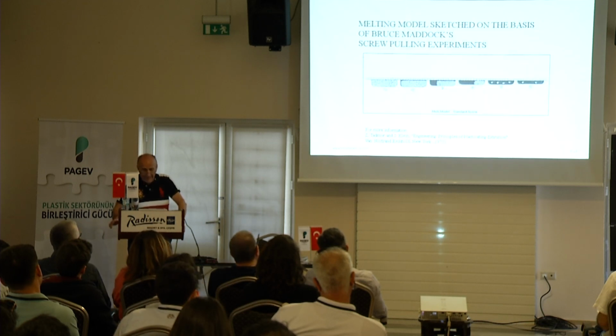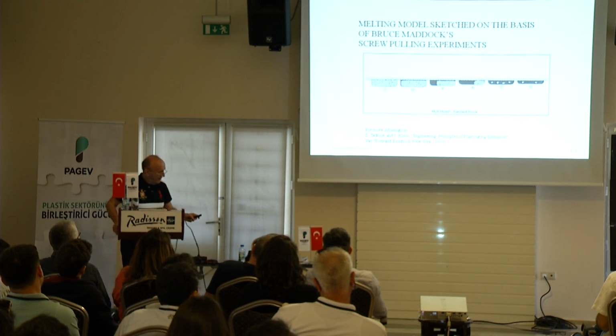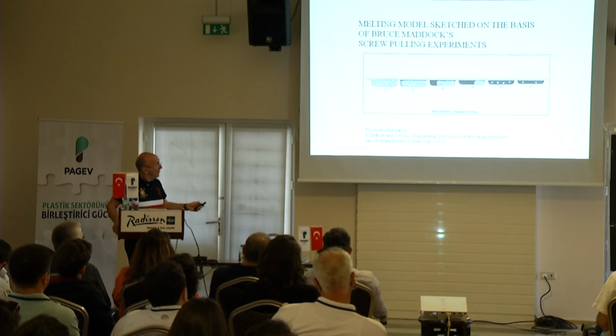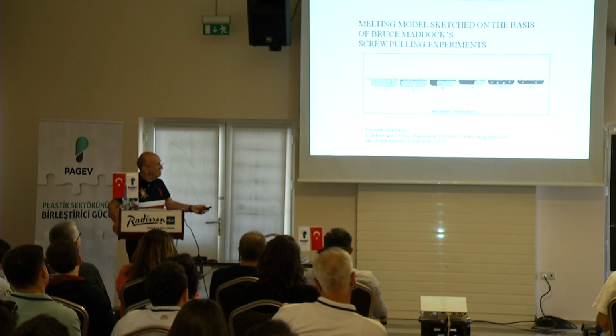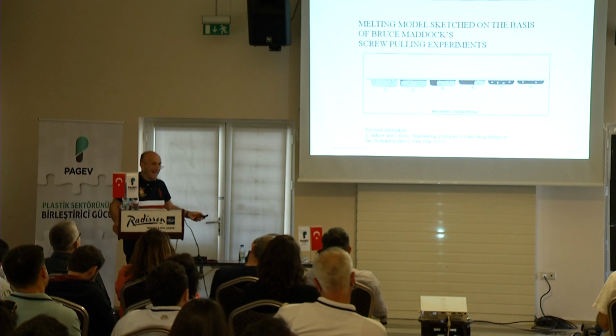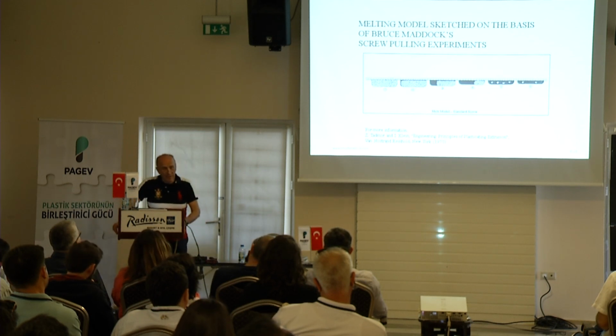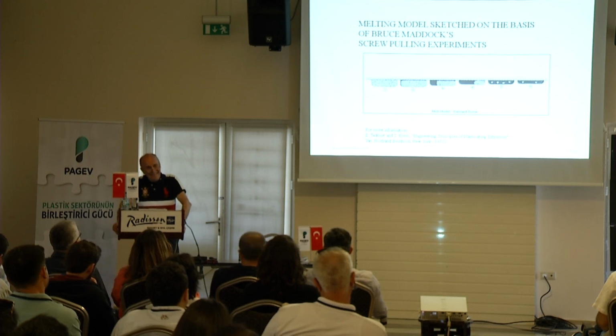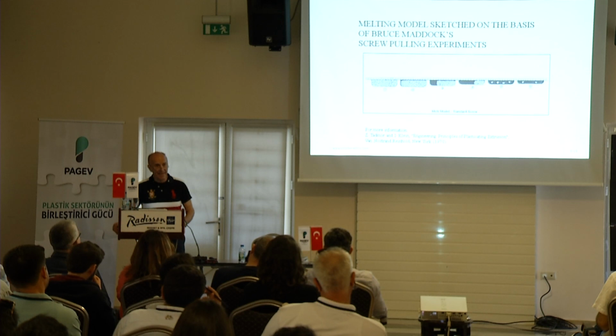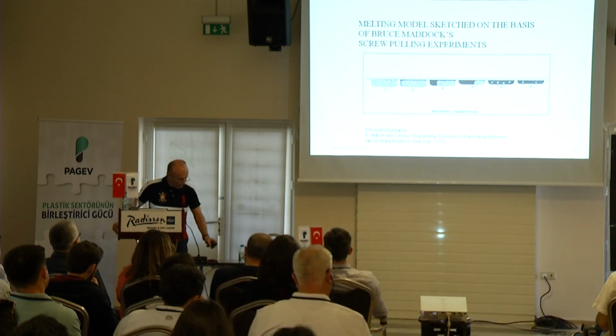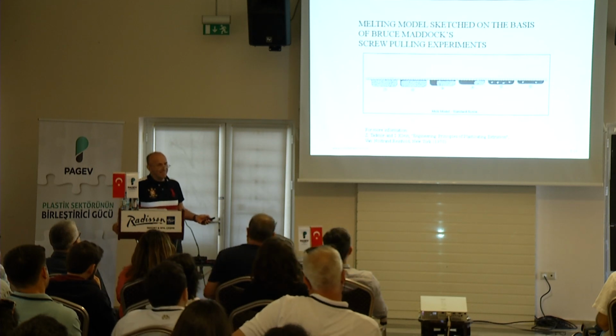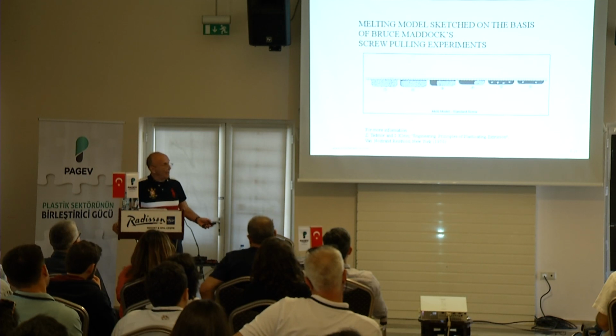So that's the standard way of melting. And here I have a sketch, and you can see the sequence of solid bed transport. Right here, you have a small melt pool. The melt pool is increasing, and so forth. However, you do not like the breakup of the solid bed, because for melting to occur, I need shearing of the solid bed against the wall. Now, if I have broken up particles like in this sketch, they do not melt. And if they do not melt, they're going to end up in the extrudate.